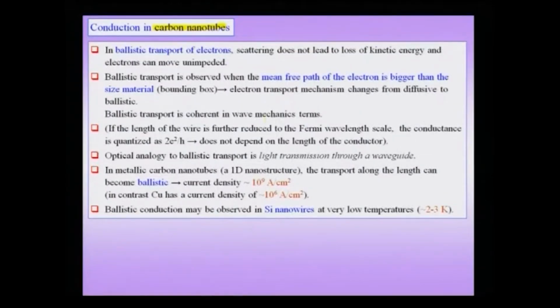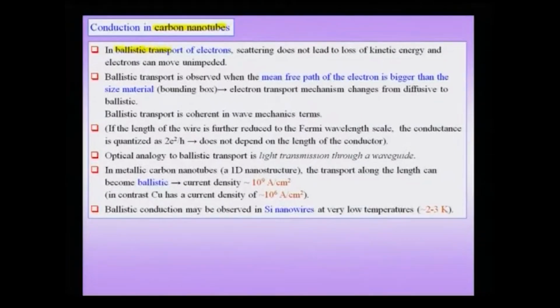And when there are no scattering events within the system, then the electrons can just keep on gaining velocity, and that implies that you can have what is known as ballistic transport of electrons. Scattering does not lead to a loss of kinetic energy, and the electrons can move unimpeded through the system. Ballistic transport is observed when the mean free path of the electron is bigger than the size of the material, and in these cases the electron transport mechanism changes from diffusive to ballistic, and ballistic transport is coherent in terms of wave mechanics or quantum mechanics.